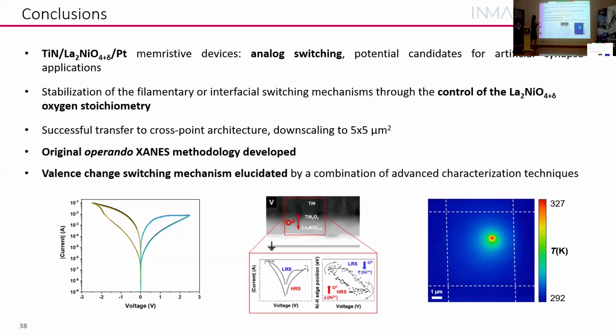Okay, in an ideal device, you're applying the voltage from here to here. However, really, normally from top to bottom, the voltage drop is not linear. If you have an interface, as we have, that is really oxidizing, we believe that the highest voltage drop is here because this is a semiconducting material. So even, well, I'm measuring from here to here. So I'm measuring the total voltage drop, but I don't know exactly how much drops here and how much drops here. And we believe the largest drop is in this oxynitride layer. I don't know if I've answered your question.